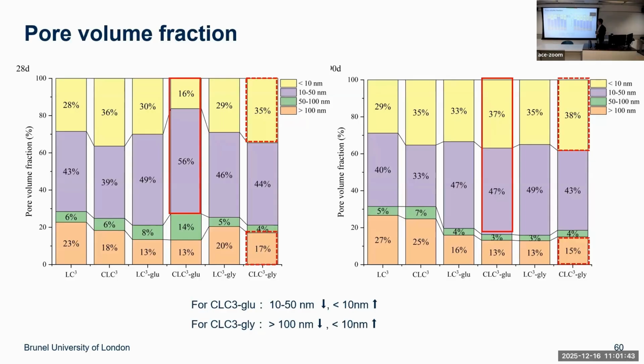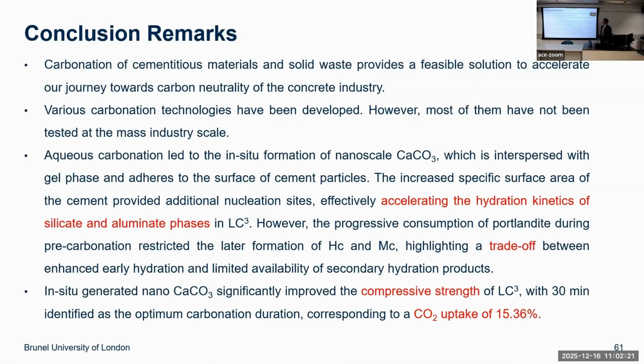And pore volume fractions with different pores. These two pores together are less detrimental. For glutamic in this carbonated LC3, the 10 to 50 nanometer pores increase and the larger pores decrease. With glycine, pores bigger than 100 nanometers decrease, but pores less than 10 nanometers increase. This can actually explain the behavior of the material.